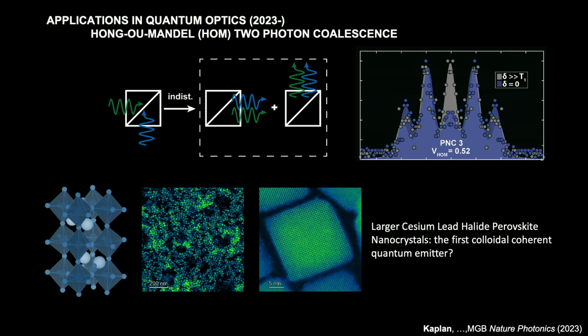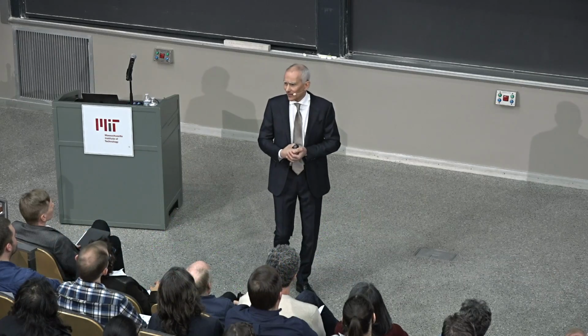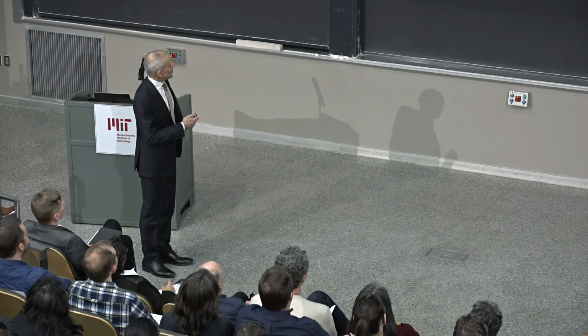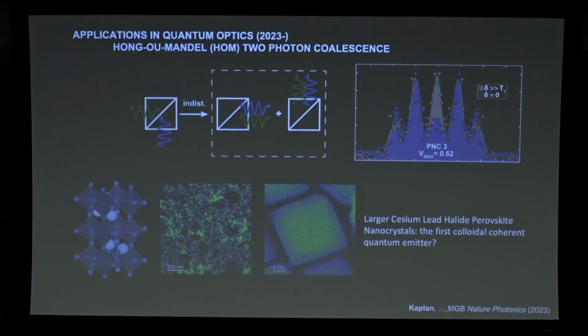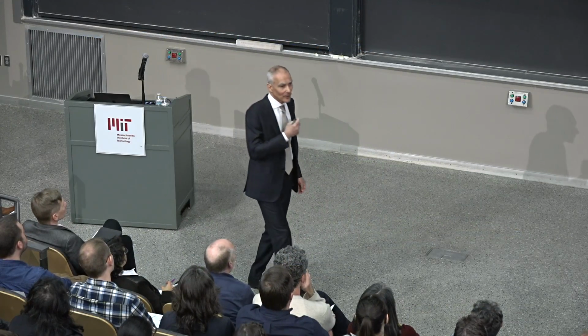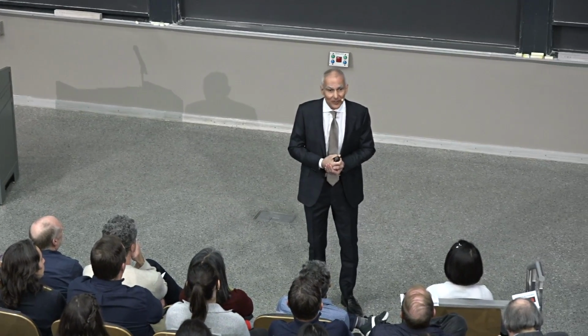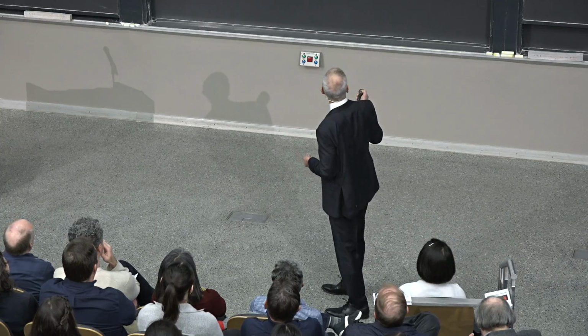More recently, this is now going 25 years ahead, by looking at individual photons from, in this case here, cubes of cesium lead halide perovskite particles, we're finding that they can emit what we call indistinguishable photons. And these indistinguishable photons, in the presence of a beam splitter, can coalesce together. This was the topic of a Nobel Prize a few years ago in physics, I think actually last year, 2022. This experiment here, for the cognoscenti, tells you if they're indistinguishable, the central peak here should go to 0. If they're distinguishable, then it goes to 100%. And the fraction here tells you how many pairs of photons that you're measuring are actually identical to each other. So we have what we call a visibility of 50%, which without doing anything special is actually pretty good. There's a lot that can be done now to make this go from 50% to 0.